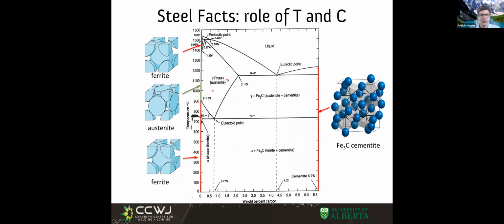I don't need to just put too much carbon. I can have a constant amount, say 1%, and as I cool down I'm in this single phase of iron with carbon in solution. When I cross this line during cooling, my solubility limit changes, and now I precipitate this cementite.